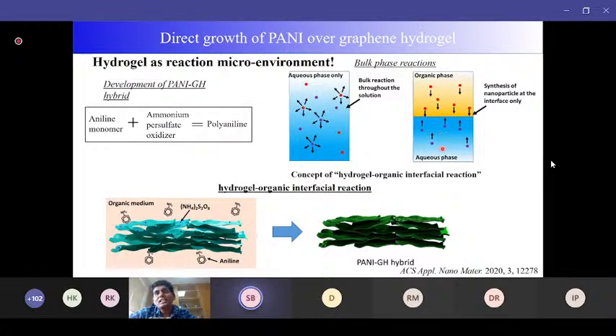So we took this as an idea. Can we replace this aqueous phase with a hydrogel? Because a hydrogel is some kind of membrane within which water is entrapped. So we remove this aqueous phase and put a hydrogel over here. Then the reactant has to pass through the channels inside the graphene hydrogel structure. Whenever it diffuses through, it can interact with the graphene surface, and the diffusion of those reactants will be much slower even compared to the aqueous organic phase, because there the diffusion is limited by the interface. In our case, when we use a hydrogel instead of an aqueous phase, the diffusion is also limited by the interaction of these molecules with the graphene.